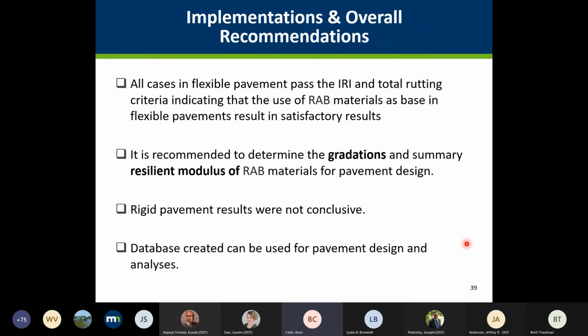Here, I think what we would recommend really is to determine the gradations and summary resilient modulus of recycled aggregate base materials. But with this database, if you don't have the capacity or time to do MR value, by just determining the gradation characteristics, you may be able to predict the resilient modulus values.